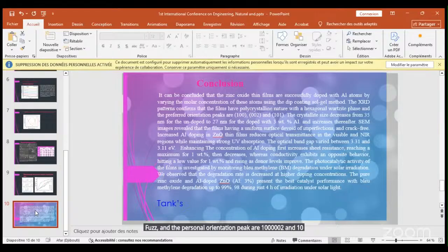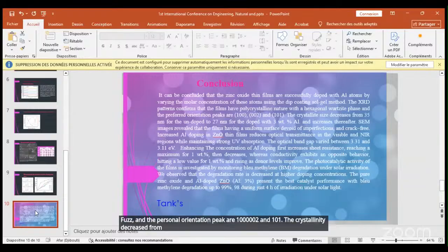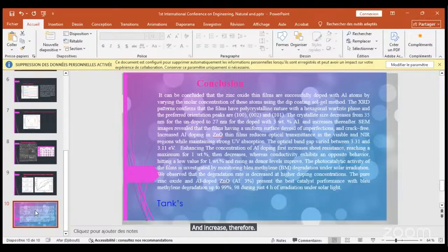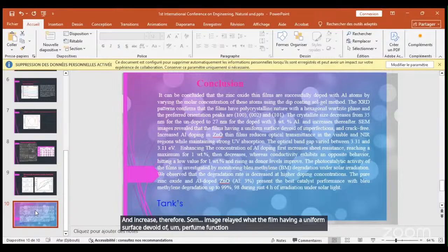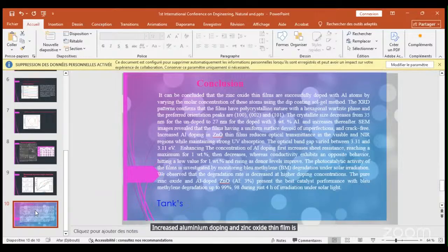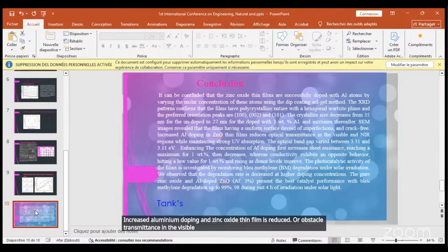The crystallite size decreases from 35 nanometers for the undoped zinc oxide to 27 nanometers for the film doped with 3%, and increases thereafter. SEM images revealed that the films have a uniform surface devoid of imperfections and crack-free. Increased aluminum doping in zinc oxide thin films reduces optical transmittance in the visible and near-infrared region while maintaining strong UV absorption.